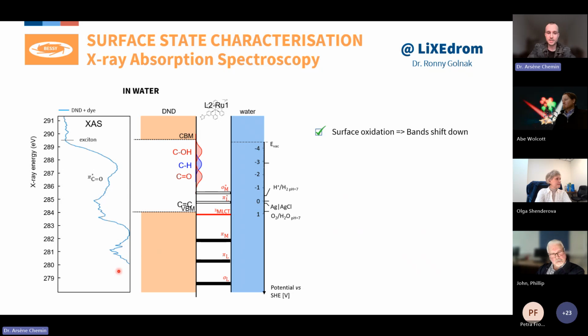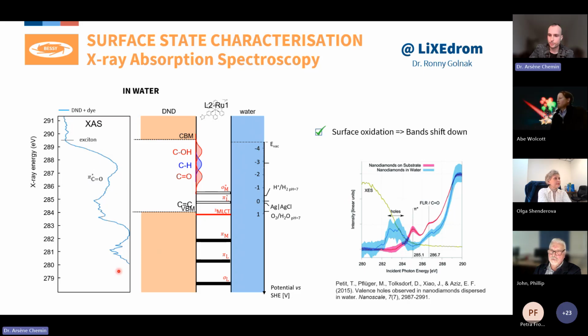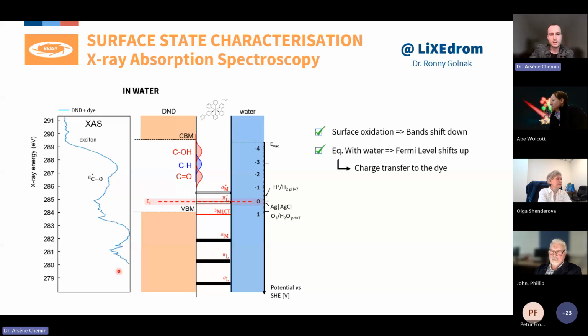And that is quite interesting because it was already observed a few years before by Petit et al. And this is a demonstration that we do have a charge transfer between the nanodiamond and the environment. That is the publication of Petit in 2015, who observed it first. And if we look at the equilibration with the water environment, we can deduce that the Fermi level in liquid is raised very much, so much that actually the 3MLCT state of the ligand is populated.